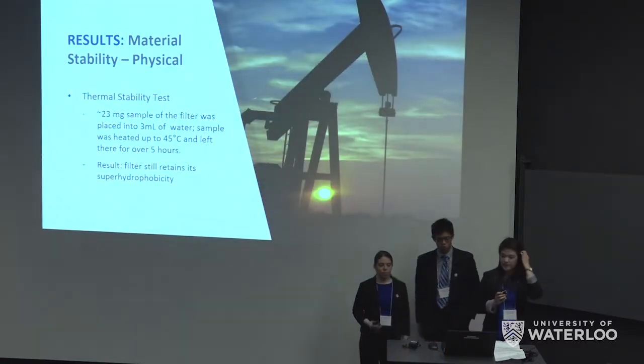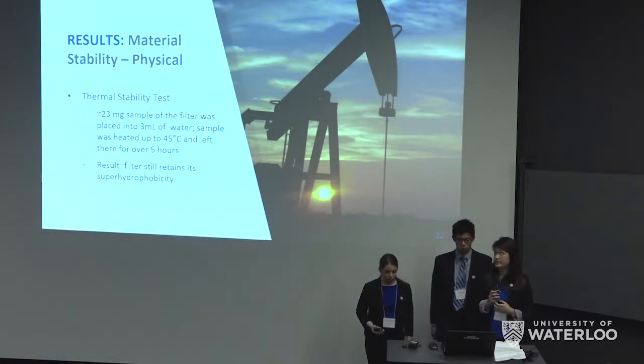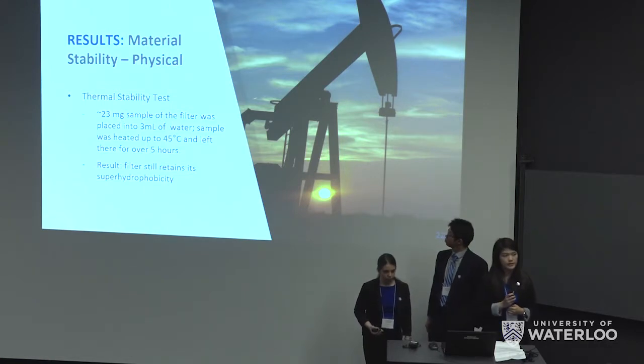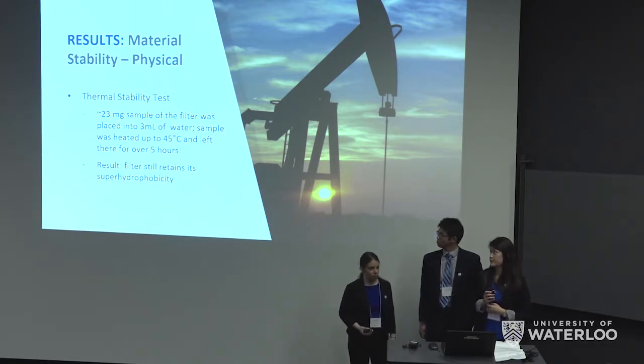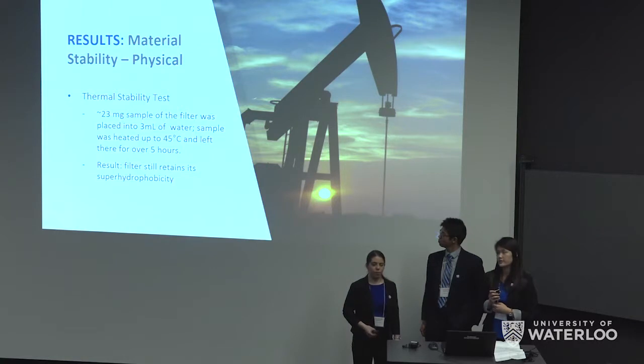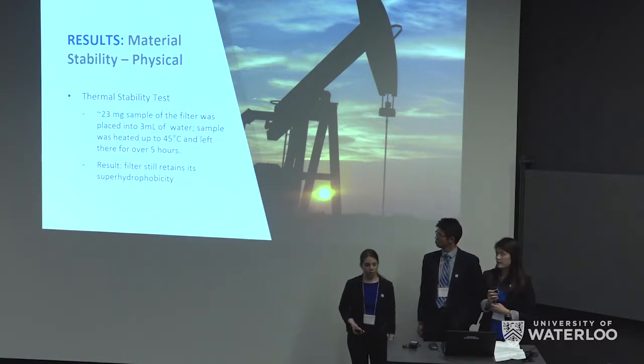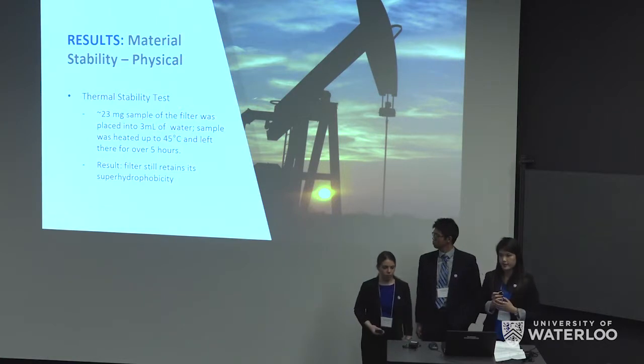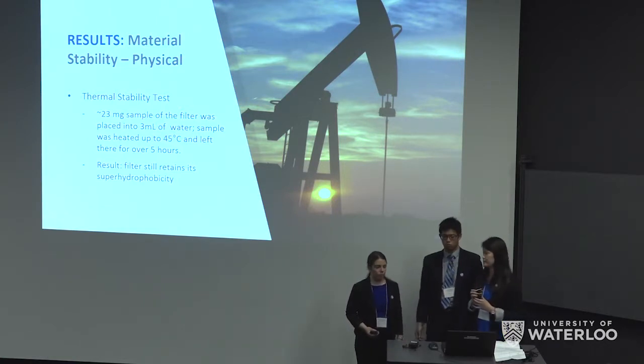The last stability test that we did was a physical test. We wanted to make sure that our material would be stable at a higher temperature. So we subjected our material to 45°C water and left it there for over 5 hours. And we found, again, that there was no degradation at all, meaning it was still stable.